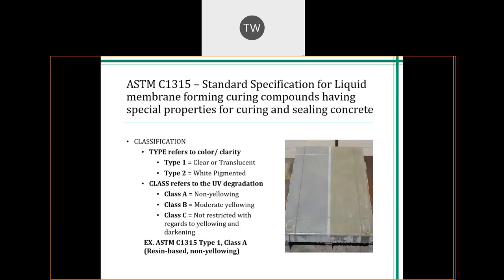And at this point, I should mention more about what a cure and seal is. So the cure portion of the name means it can be used as a liquid curing membrane for concrete. This material must be able to form a film on the surface of your fresh concrete, and what it's going to do is hold in only a portion of the mixed water to aid in that cement hydration process we talked about. That remaining unused water is then allowed to evaporate through the membrane at a controlled rate. Without this process, your design strength might not be developed. The seal portion in this name means it functions as a sealer. As a sealer, it protects the concrete for a period of time. Curing and sealing concrete are different processes and are performed at different times in the life of your concrete.